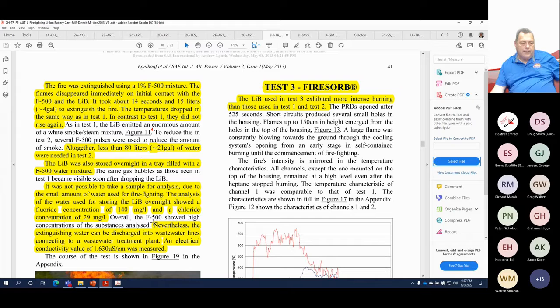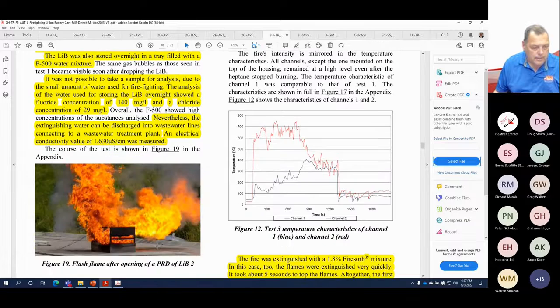But this is one of the big differences between using plain water and using an encapsulator agent. We have 3 separate test reports that are showing that with the runoff from an encapsulator agent, you're not creating hydrofluoric acid like you are with water, and that the runoff from an encapsulator agent extinguishment can be diluted down and run through a municipal or industrial wastewater treatment plant. On the other hand, the stuff with water needs to be treated.